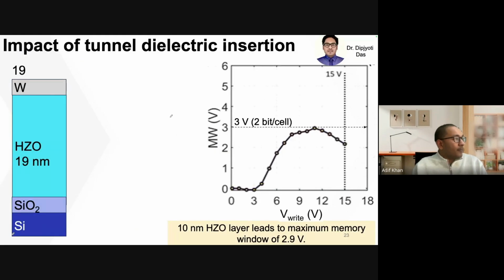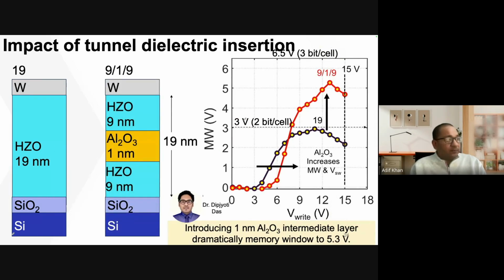All right. So the first thing is that, remember, we had a thickness limit of 19 nanometers for this gate stack. So the first thing that we did was to deposit 19 nanometers of hafnium zirconium oxide, a very well-known ferroelectric material. And this is how the memory window versus voltage characteristics look. You can see that as you increase the write voltage, the memory window goes up, up, up, but it reaches a maximum value of 3 volts. So clearly we needed 6.5 volts, and we are having 3 volts.